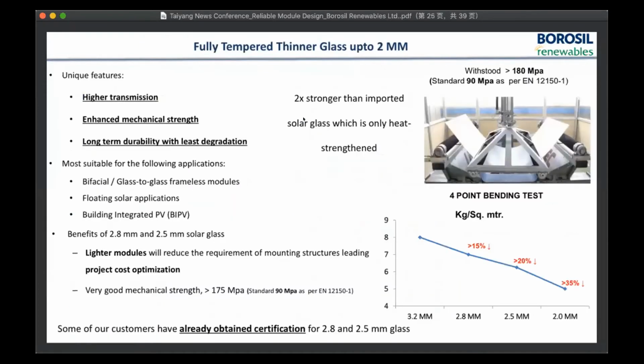Next slide, please, Neil. So as I was talking about the 2 mm fully tempered thinner glass, Borosil has been the first solar glass manufacturer to supply this thinner glass to module manufacturers, making it fully tempered as compared to the heat strengthened glass that has been supplied to the market. So what are the unique features of this thinner glass, including 2 mm? It has slightly higher transmission because of the lesser material, enhanced mechanical strength, and long-term durability, basically due to lower EID. And as we have been seeing during the past slides, for bifacial and glass frameless modules, they'll be more suitable to floating solar applications and building integrated PV, which has been dominated by the thicker glass of 4 mm and beyond.